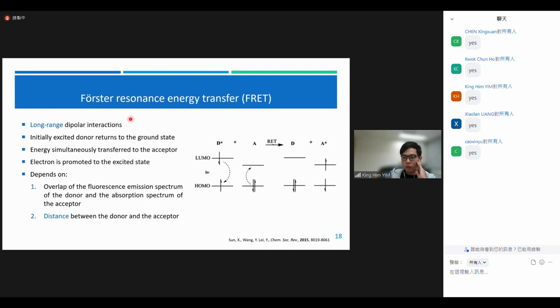So this one is different from PET because PET is concerned with electron transfer, but FRET is concerned with energy transfer. And that's why the distance becomes longer compared with PET. For FRET, it can transfer the energy up to 100 Angstrom. And this FRET strongly depends on the overlap of the fluorescent emission spectrum of the donor and the absorption spectrum of the acceptor, and also the distance between the donor and acceptor. So these two points are important.